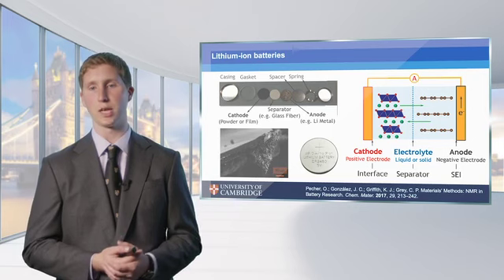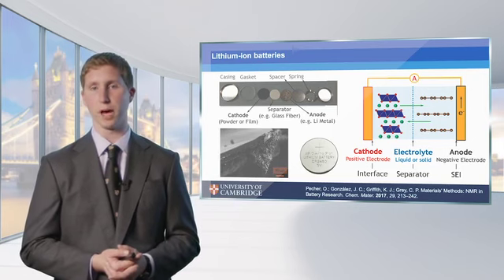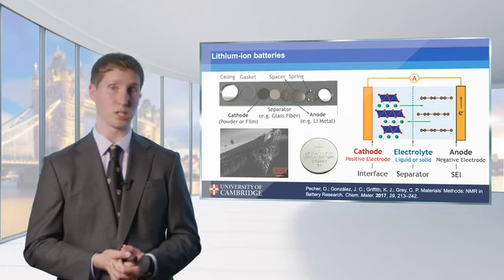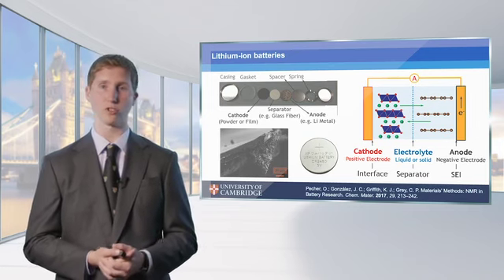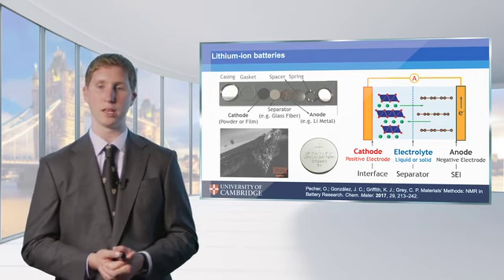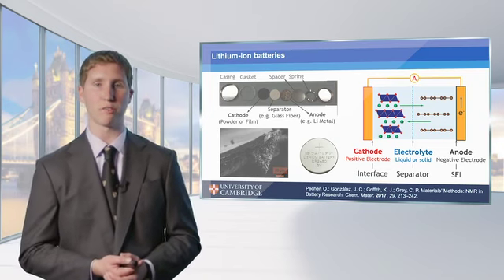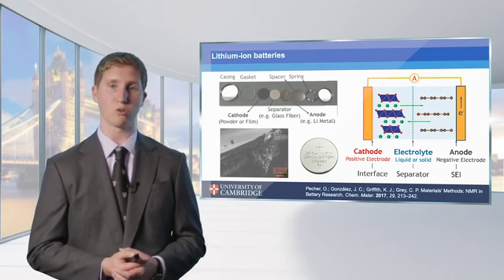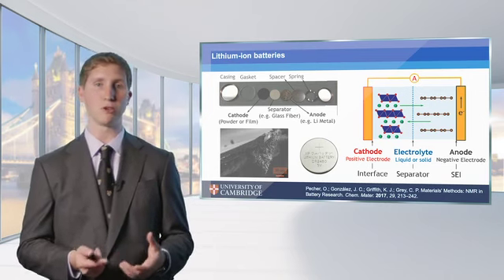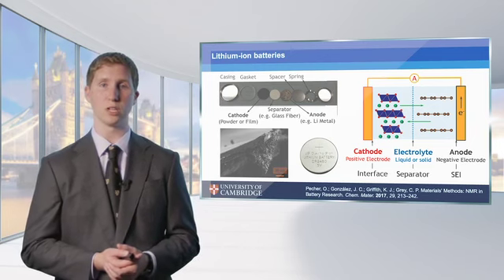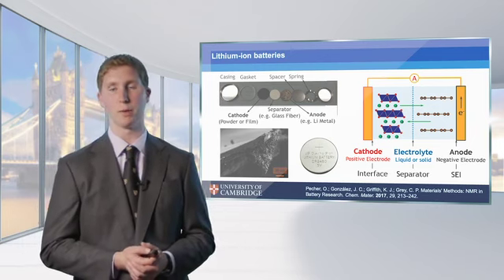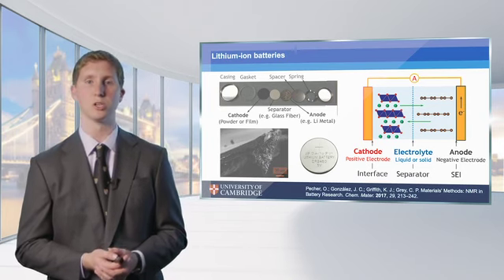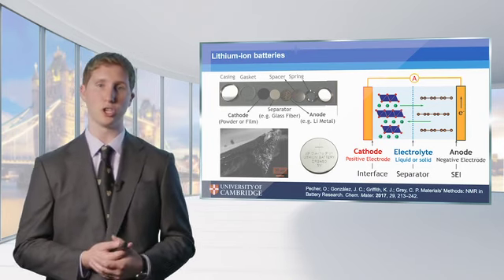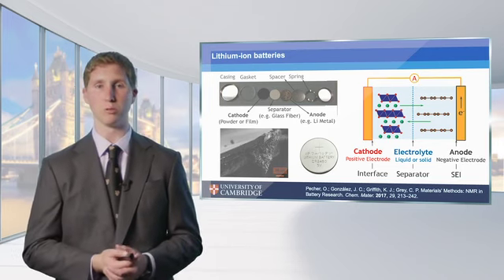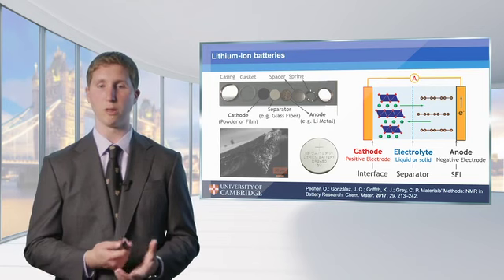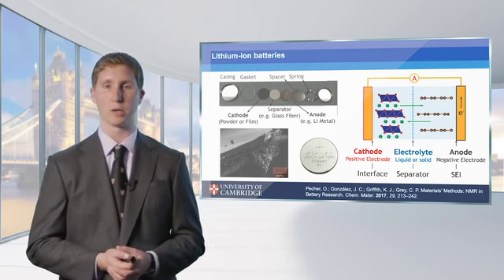If we try to operate a conventional battery with a graphite electrode at a high current density, so we try to charge it fast or extract high power out of it, then there are risks to damaging that graphite structure. In particular with fast charging, there are risks of plating lithium spindles or dendrites onto the surface, and those dendrites can short circuit the cell and lead to a battery fire or explosion. So there are real safety issues if we tried to charge graphite too fast, and there are engineering controls that currently prevent you from doing a 5-minute charge. But if we could develop new materials that enabled us to do that, we could eliminate those safety issues.